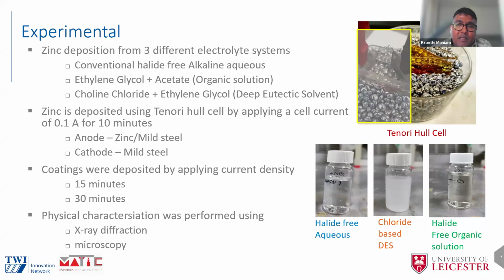What we have done is we deposited at different temperatures and different cell currents. From there, we derived the current densities, and we chose the optimal current density from that and tried to understand the nature of the deposits and their growth. For that, we chose two timings, 15 minutes and 30 minutes, and we characterized the deposits using X-ray diffraction and microscopic methods.